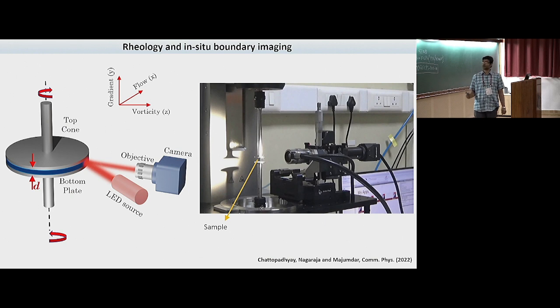To see what is going on, we use boundary imaging. This is the schematic setup. We put the dense suspension between two plates, which are rotating in opposite directions. This is the actual setup in the lab. You put the sample between these two plates, illuminate the boundary, and then image the system. The particles are opaque, so we cannot look inside the sample.